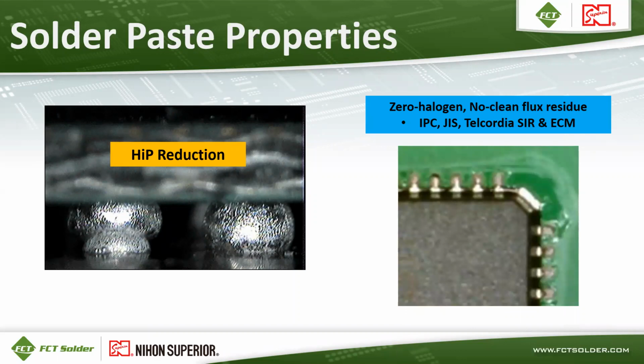And then also important, of course, for no-clean solder paste is the flux residue and what's in that flux residue. How reliable is that? In this case, AMP1 PT is a zero halogen, no-clean flux. It passes IPC, JIS, and Telcordia SIR and ECM tests. Of course, there are lots of different varieties of SIR and ECM, but these are 3 of our common industry tests that are pretty aggressive and rigorous. And we want to make sure the flux passes all of those tests.